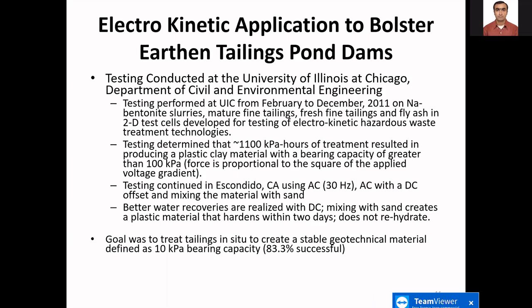And one thing that is to quantify this, we looked at the bearing capacity relative to the moisture content, and found that at a variety of moisture contents, the tailings after treatment exceeded the 10 kPa requirement, and it was 83.3% of the samples that did this. So we think that we could bring it up to probably 90% by adjusting during the treatment system and trying to achieve an optimal application of the electrostrictive force.